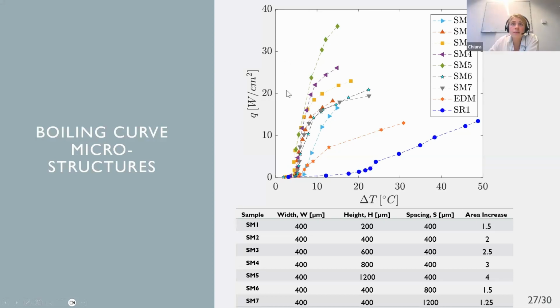Yeah, so the temperatures are measured with thermocouples, and we calibrated them. We didn't use the manufacturer calibration, but we calibrated them in situ in a water bath. So the uncertainty on the temperatures goes down to 0.1 degrees.